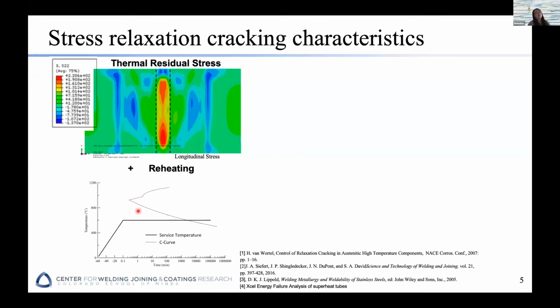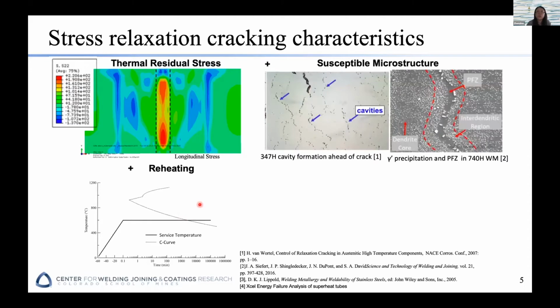Okay, and then when you put the material at a high service temperature, for example 600 degrees Celsius in this case, by doing the simulation, we can see this is the transformation temperature for the niobium carbon nitrides to form. So apparently, if you put the material at this service temperature, the niobium carbon nitrides will start to form. And when they form, they preferentially form along the grain boundaries as coarsened precipitates, and some of them will form within the grains. Okay, so this is at a scale of roughly a few microns.